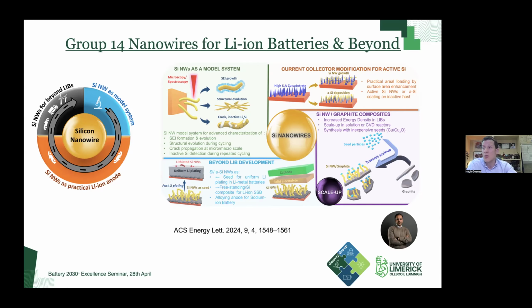So this has grown from a really rich literature around CVD growth of silicon nanowires, but one of the main challenges with that was getting to the areal capacities that you would need in a practical system. Okay, so we need to be up around 3 or 4 milliamp hour per centimeter squared at least in terms of those systems. And if you grow a very low loading of these silicon nanowires, you just won't reach those.